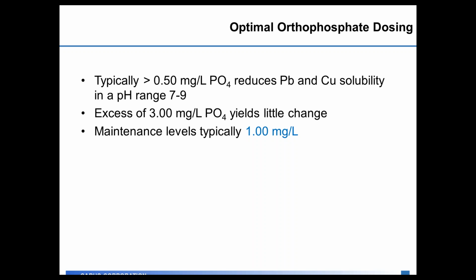Most systems, depending on water quality, can have a maintenance level of around 1 milligram per liter as orthophosphate in the distribution system. Things that would cause the dosage to be higher toward 2 and 3 milligrams per liter, as you tend to have lower pHs and lower hardness in the water, you need more of the phosphate to help form that coating in the distribution system, and so you'd increase your dosage from 1 milligram per liter up to 2 or 3 milligrams per liter based on that water quality in the distribution system and have the higher dosages.